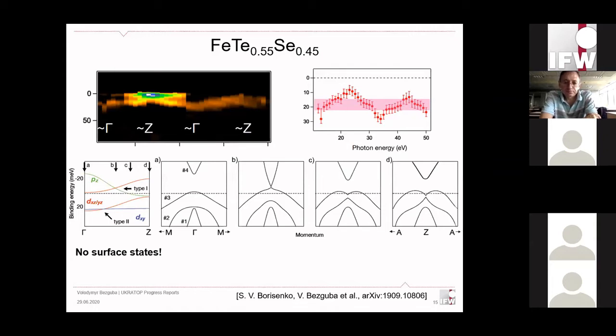And it is even not too hard to see how the group who were reporting seeing topological surface states could have made a error here. If you look at the pictures below from A to D, these are our scenario of what is going on in iron tellurium selenium. If you look at these pictures from A to D, you can see that bands 1, 2, and 3, while they go from gamma to Z over the Brillouin zone, they almost don't change. Therefore, we need a very, very sensitive experiment to actually catch any differences. And that's what we managed to do, luckily.